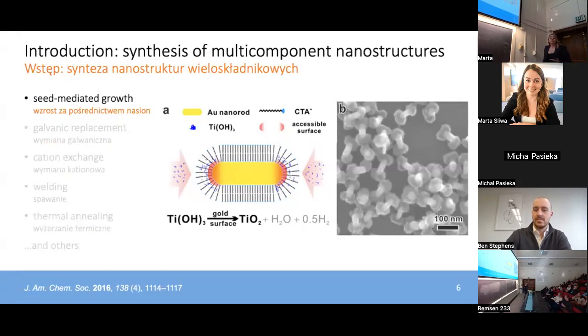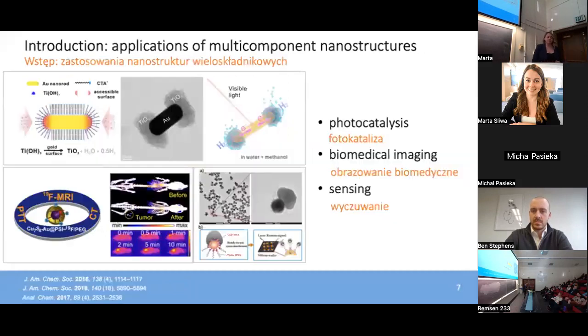So just to go into a little bit more detail about one of these approaches, seed-mediated growth here specifically, is used to create these titanium dioxide capped gold nanorods. So in this particular system, the curvature at the tips of these nanorods makes the ligands or the molecules that stabilize these nanorods less dense. That lower density allows for the TiO2 or the titanium dioxide precursors to come in at the tips, and we eventually yield these gold titanium dioxide nano dumbbells, as they call them, as we see in this micrograph here.